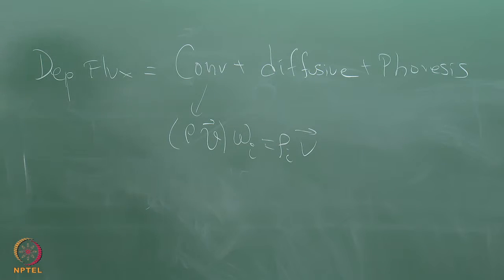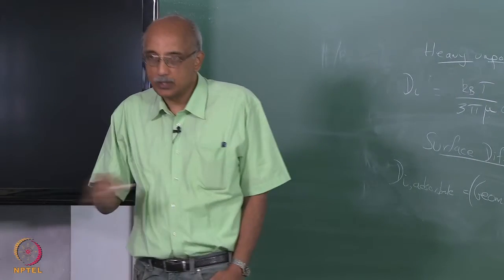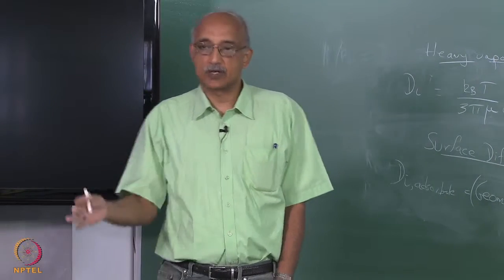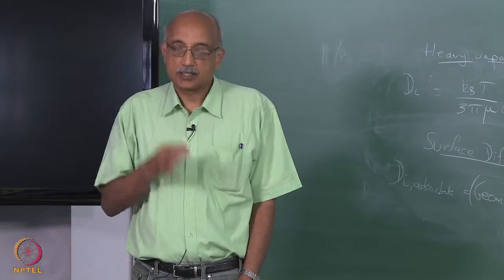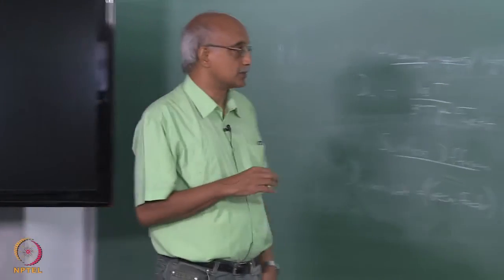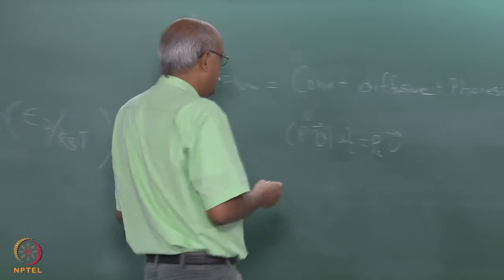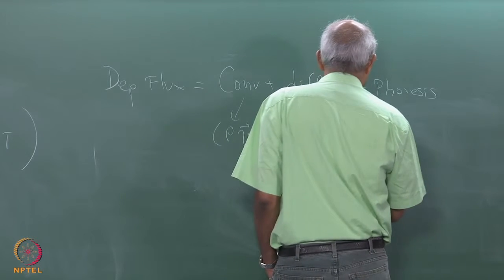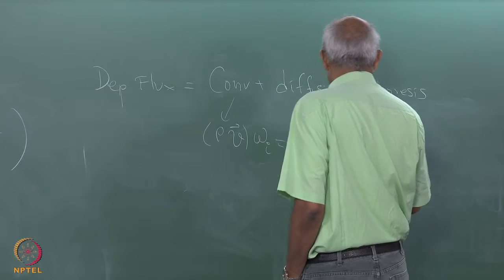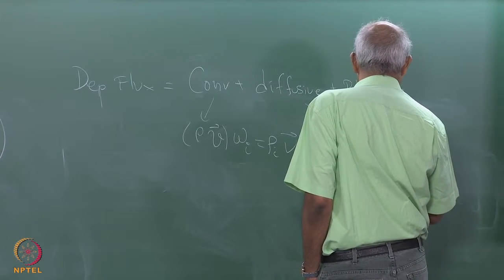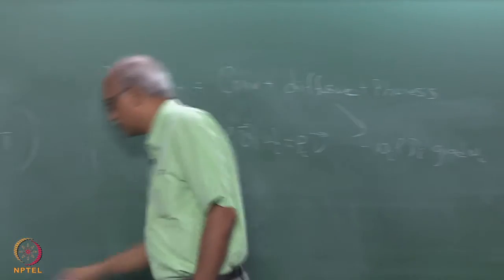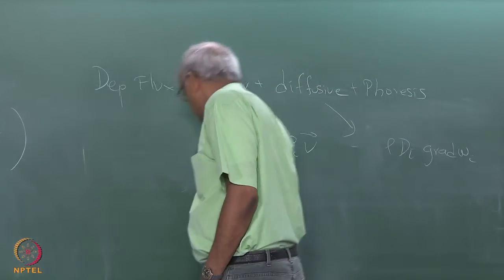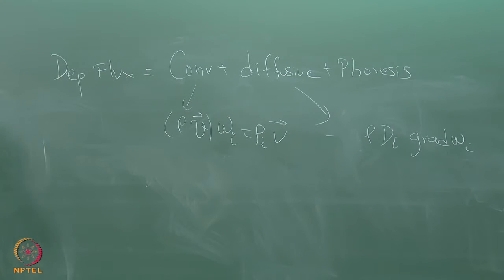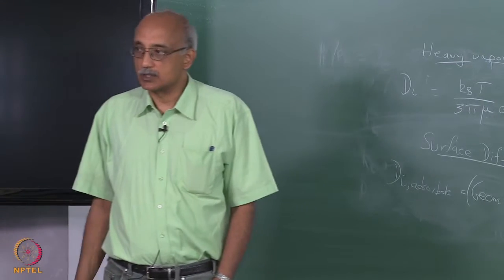So, the convective flux is associated with molecules that are essentially following the motion of the fluid itself. They are just moving along with the carrier fluid, but because the carrier fluid has a velocity and a mass associated with it, there is a convective flux of the depositing species also. And we just saw that the diffusive flux can be expressed as minus rho D_i gradient in omega_i. So, once you know the diffusivity of the diffusing species and you know its gradient, you can calculate the diffusive flux.